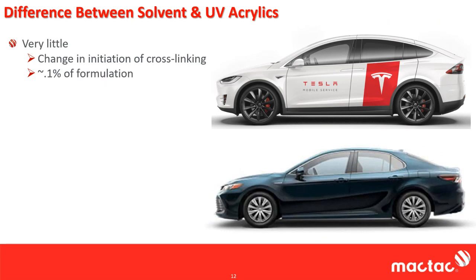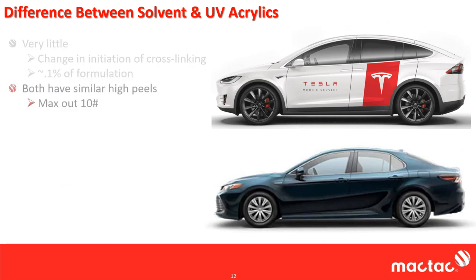Well, they're actually the same, and in a lot of cases, some of the vendors out there we worked with just simply took an old solvent adhesive we had, removed the thermally initiated cross-linker, and put in a UV cross-linker. Everything's basically the same, except we just changed how those 2 adhesives cross-link. Again, they're still cross-linking, it's just a change in how it happens. And what we see is, they both have similar peels. There are solvent adhesives out there that have high peel. There are UV adhesives out there that have high peel.